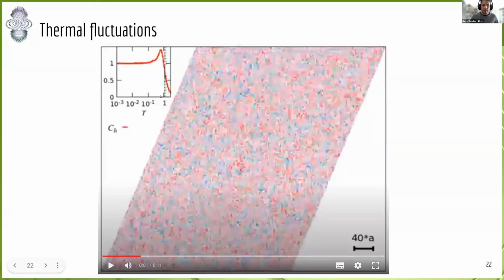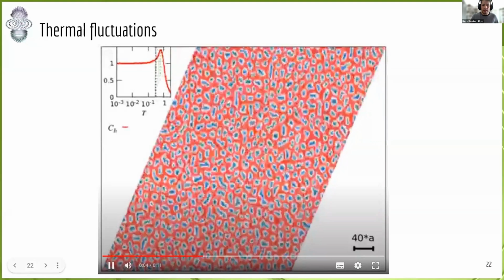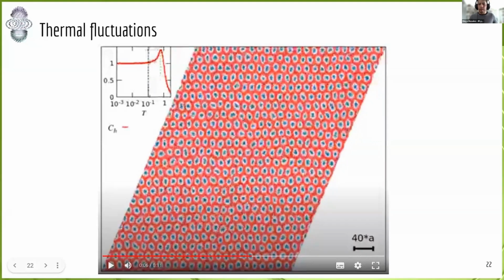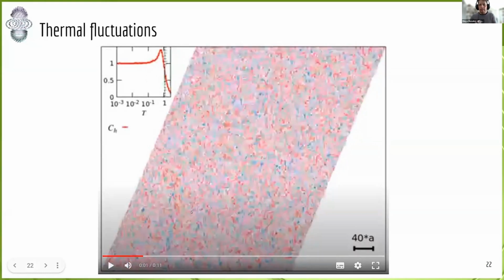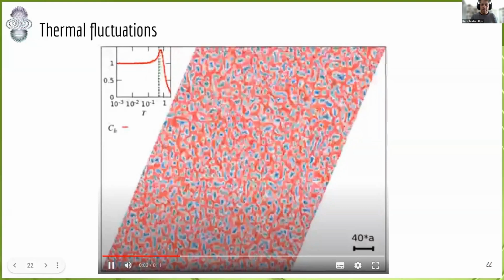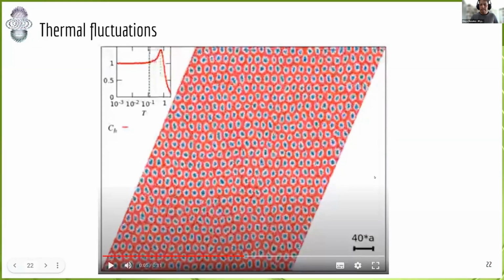This is the specific heat versus temperature. This is the lattice. The color red corresponds to spins out of plane along the field direction, and blue to the opposite direction to the external magnetic field. I will start in the paramagnetic state here, a temperature in the paramagnetic phase without any kind of order. And you can see that now, after the phase transition, we arrive at the skyrmion crystal or skyrmion lattice. The point here is that at high temperature, we have a disordered state without any kind of order. After the phase transition, we arrive at the skyrmion crystal.